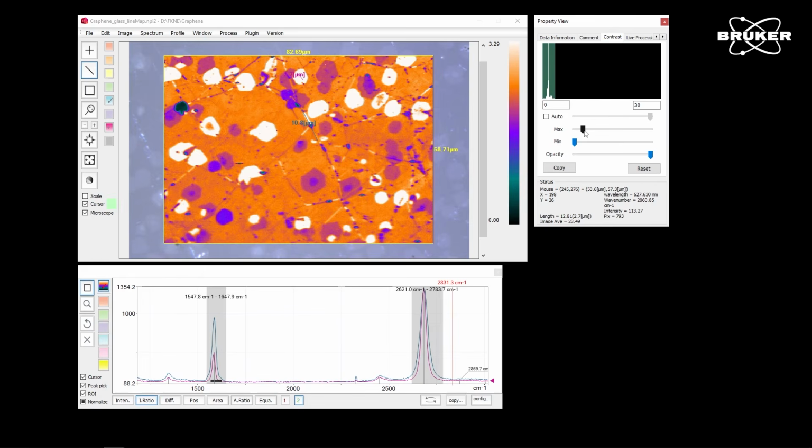From the values we are getting, green and black, if there is some, would be multi-layer. Purple would be a bilayer, because that would be around 1. And orange would be everything that is a monolayer.